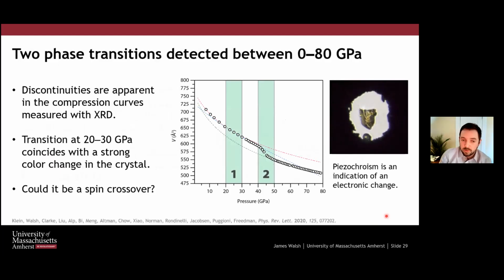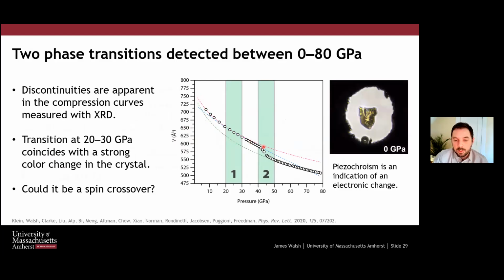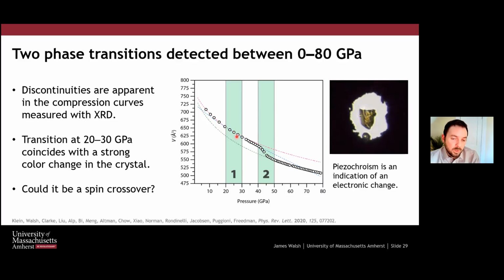And so what we find, this is a plot of the unit cell volume as a function of pressure. If we look all the way up to 80 GPa, we notice two things, which are phase transitions. The dotted lines represent equations of state, and we find that in these two regions, we depart from one equation of state onto another. In other words, that equation of state cannot fit before and after these regions. And so we switch between equations of state, and we know that we've undergone a phase transition. One of them is kind of hard to see, the other one's pretty obvious. So we have these two phase transitions.